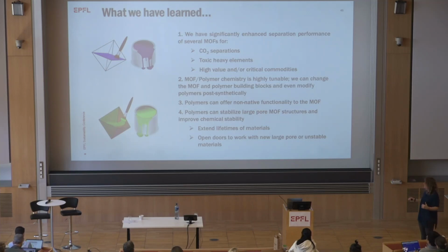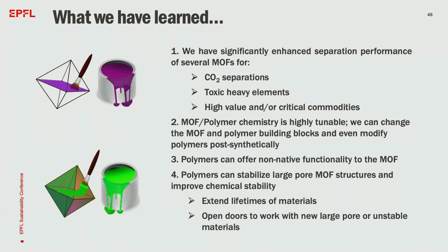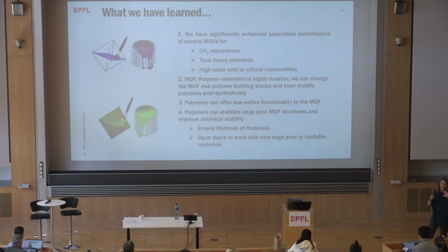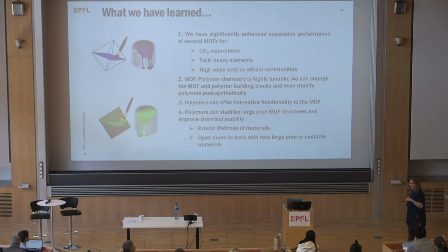Okay. So from there, what I've shown you is that we can really design these materials for a lot of important applications. I've shown you today CO2-based separations, toxic heavy elements, and high value and or critical commodities. I think these materials are particularly special because they have extremely high surface areas and they're highly chemically tunable. So we can change the building blocks in our MOF, the metals, the ligands. I've already shown you that. We can put various polymers inside. Then we've also developed chemistry that we can actually modify the polymers while they're inside the material's pores, which allows us to enhance their selectivity and things like that.